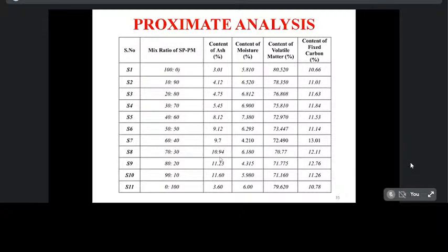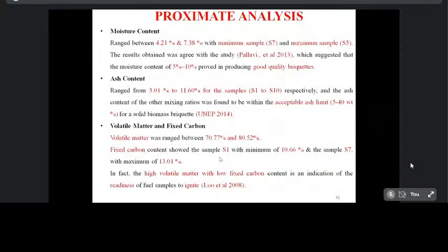Here the ash content values range from 3.01 to 11.60, and moisture content ranges from 4.21 to 6.900. The volatile matter also ranges from 70.77 to 80.520, and fixed carbon values range from 10.66 to 13.01 for sample S7. So the moisture content ranged between 4.21% to 7.38%, with the minimum for sample S7 and the maximum for